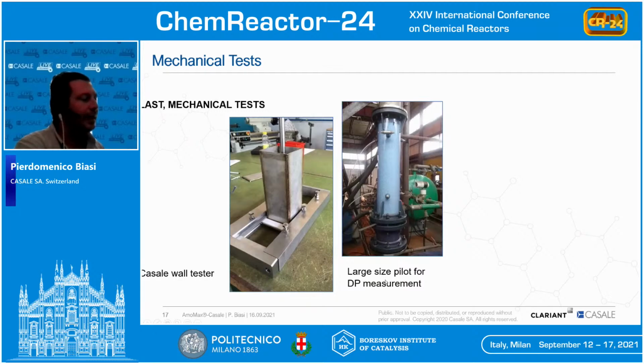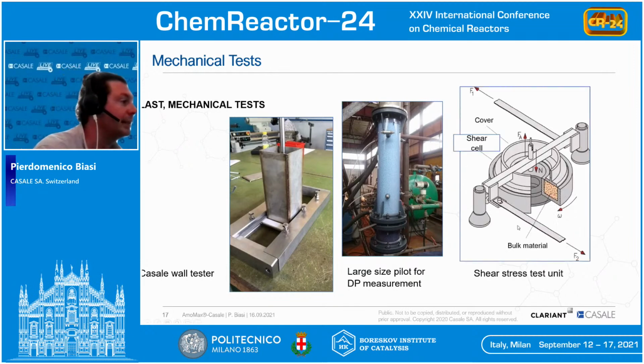Then there are also pressure drop tests that in this case we didn't perform, but it is right to mention, because you can do it with simulation, but confirmation with experiments is really important. And we also tested the shear stress, which measures the stress between catalyst particles that interact together, and how large the shear stress is.